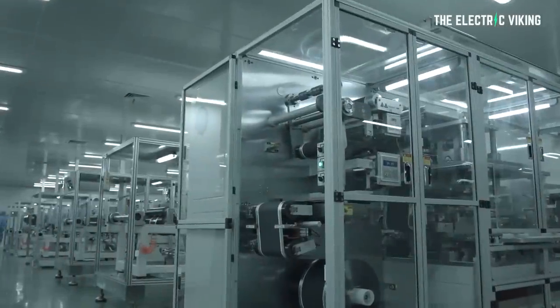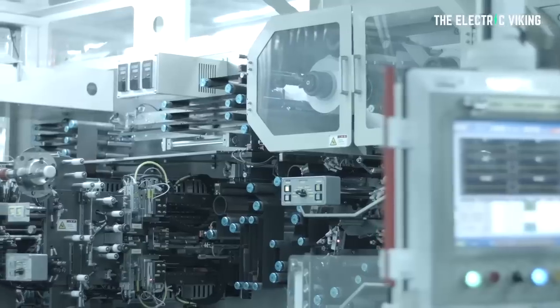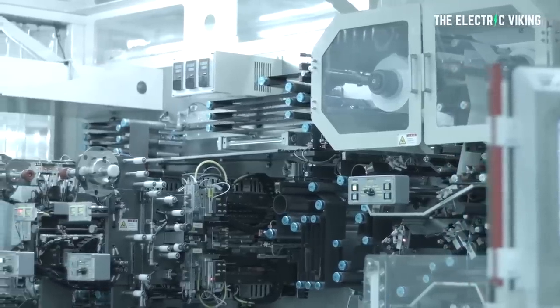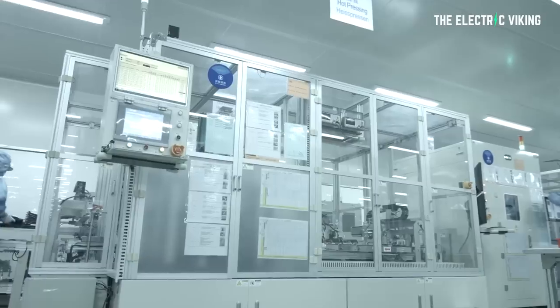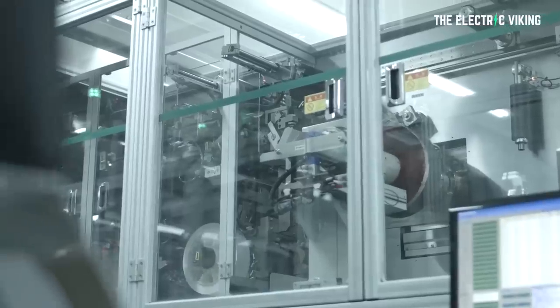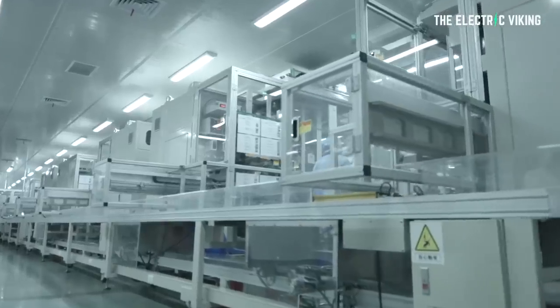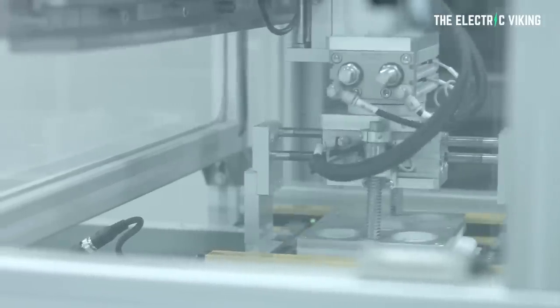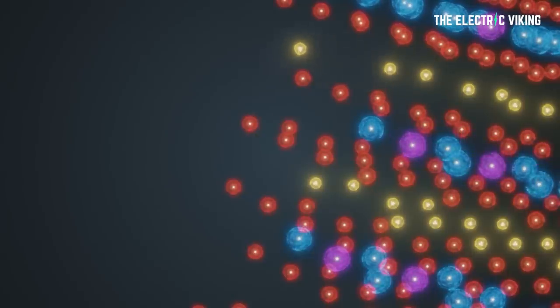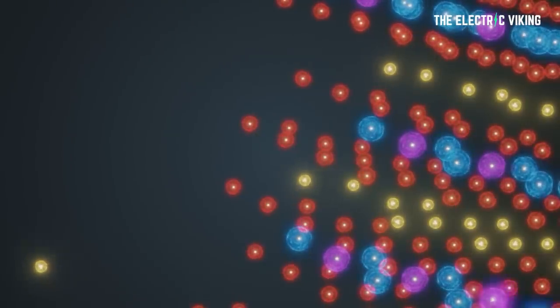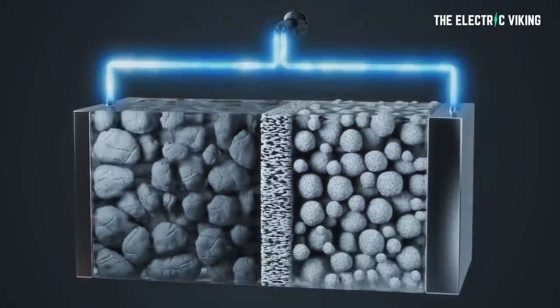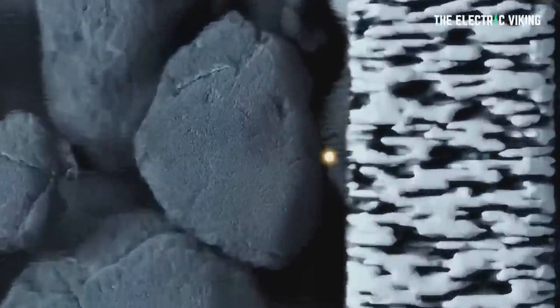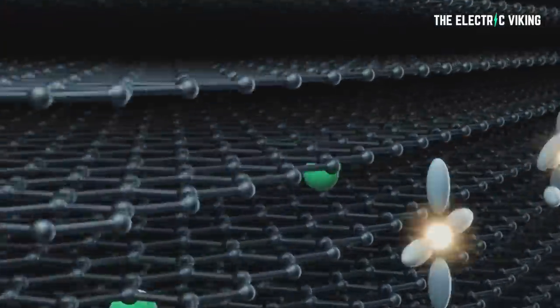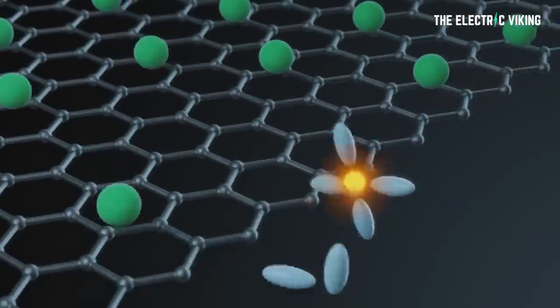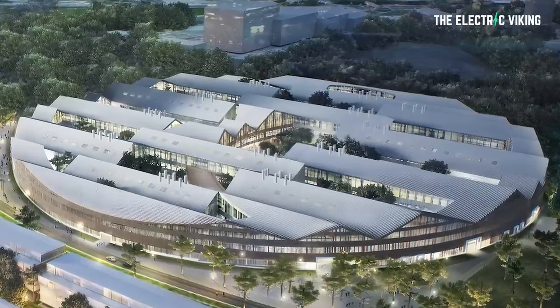Our material is a single crystal NMC cathode with spherical particles, combining the best of both worlds as far as maximizing energy density goes. Unlike polycrystals, the powder particles don't have an internal structure, so there are no wasted spaces at grain boundaries. But on top of that, you can also pack more spherically shaped single crystals into the same limited volume than octahedron shaped ones, so you get more density on that account too, study co-author Skoltech research scientist Alexandra Savina said.